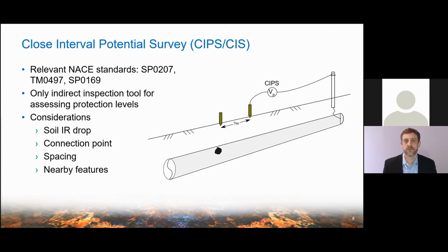So the CIPS is pretty much a mandatory part of any ECDA, and it's going to be really important to recognize where you have the possibility of active corrosion on your pipelines. Now, conducting a CIPS, basically it's like doing test post measurements, except instead of just setting up your reference electrode right beside the test post, you're walking along the pipeline and taking periodic measurements at some spacing along the pipeline. So here's your voltmeter. You've got a short lead down to your reference electrode and then a long trailing wire back. And this is completing your electrical circuit for your voltage measurement.